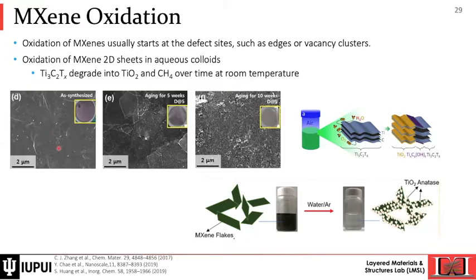This is how a MXene looks like, meaning MXene film. If you put it under a microscope and you see these dotted points, these are the oxides that you see on the flake. And that is not MXene anymore. How can you prevent MXene oxidation?